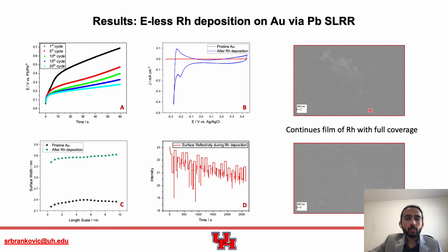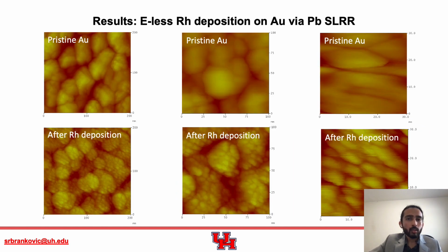And from the SEM images, we can see that there is a continuous film of rhodium with a full coverage on entire substrate. Now this slide here shows STM images for the pristine gold substrate as well as after rhodium deposition. And we can notice that the grains of the gold are covered with smaller grains of rhodium after deposition.